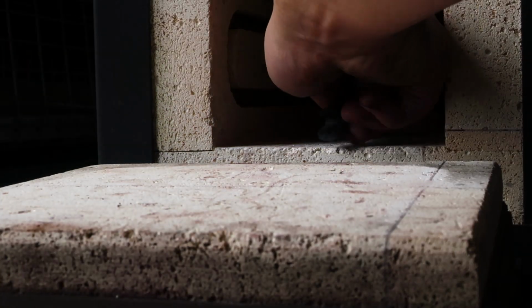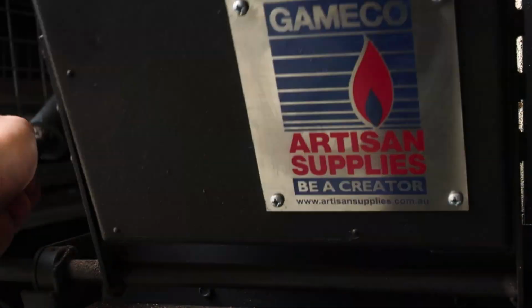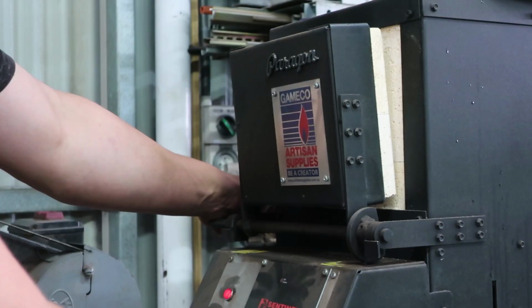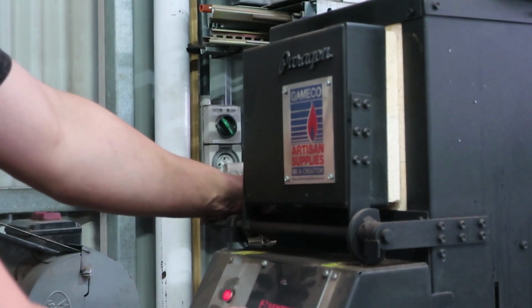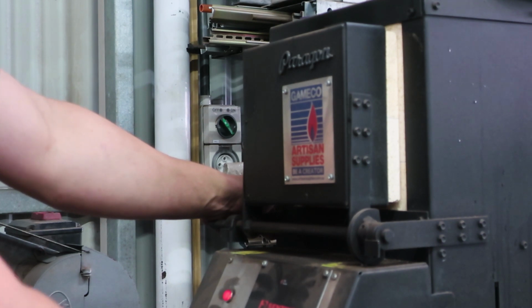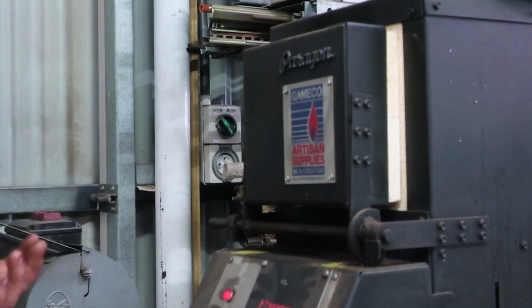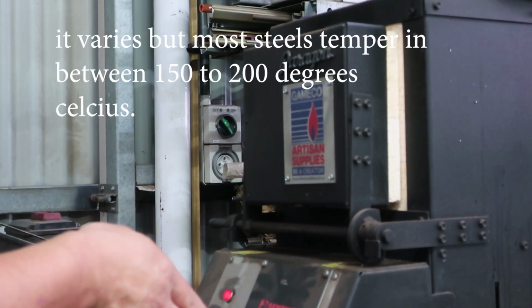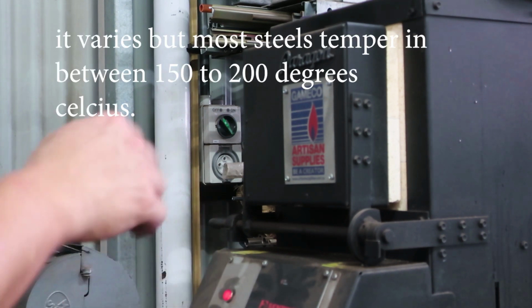But right now, I temper the knife in the kiln at 130 for 2 hours twice, which is quite low, but I temper low and test the blade and adjust the temperature accordingly. I can always go higher but not lower, that's why I go 130, but make sure you don't do anything that could snap your blade at that low of a temp range. I do this when I'm uncertain with the steel, but if you know your steel well, there's no need to do this step.